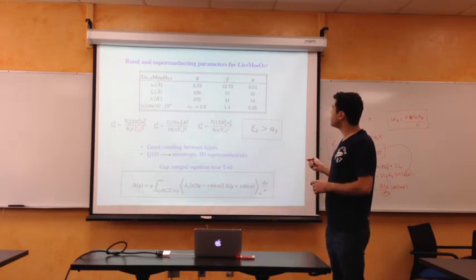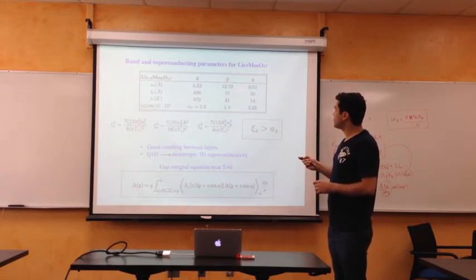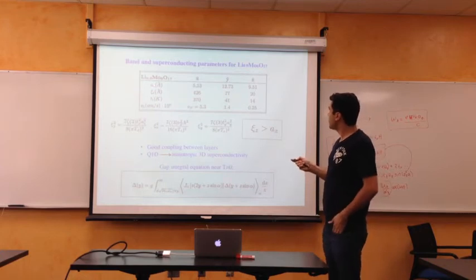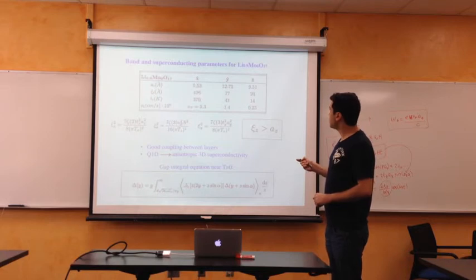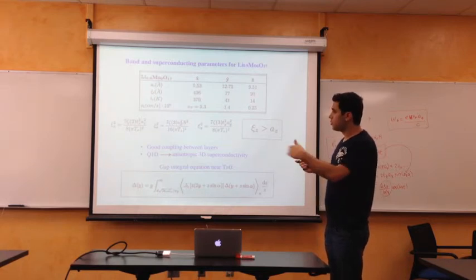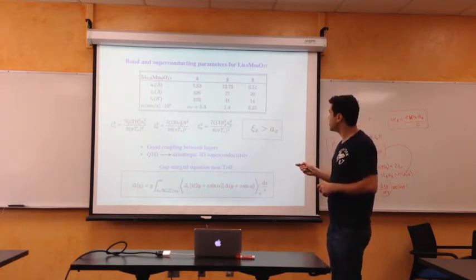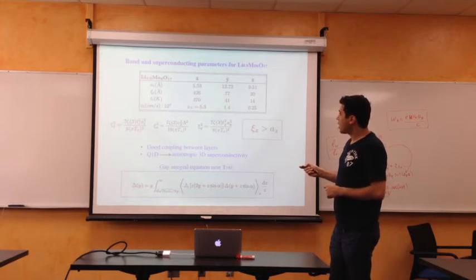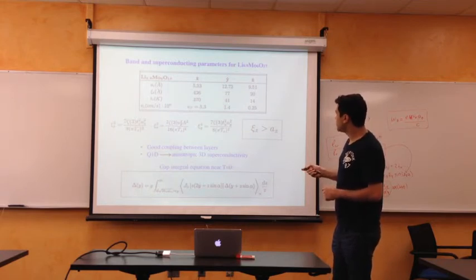And we extract all the relevant band parameters and superconducting parameters. So A are just the lattice constants. The xi here are the coherence lengths along all perpendicular directions. The electron hopping terms, T, have been calculated from Ginzburg-Landau relations.